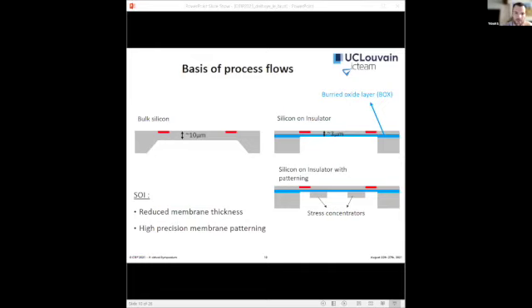Another variation of the process is to use silicon on insulator wafers with a buried oxide layer underneath the active silicon that can be used as a good etch stop layer. This allows for thinning the membrane down to 3 micrometers, since bulk silicon struggles to allow going below 10 micrometers. Coupled with dry etching, this also allows high precision membrane patterning from the backside, allowing for creating stress concentrators to increase the sensitivity.